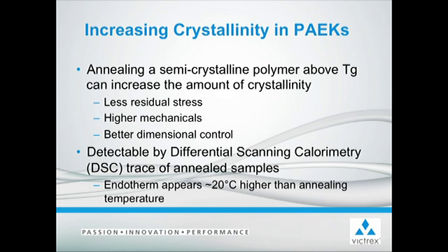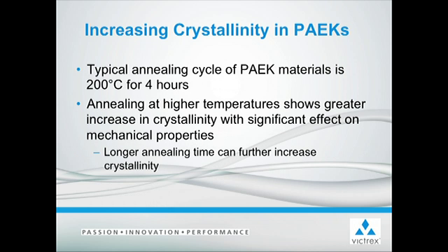Annealing, or heat treating a semi-crystalline polymer above its glass transition temperature, can increase the amount of crystallinity present. This results in less residual stress, higher mechanical properties, and better dimensional control. You can see this on a DSC trace of the annealed sample as an endotherm roughly 20 degrees C higher than the annealing temperature. A typical annealing cycle for PAEK materials contains a hold at 200 degrees C for approximately 4 hours. Annealing at higher temperatures will show a greater increase in crystallinity with a significant effect on the mechanical properties. Longer annealing times will further increase the level of crystallinity.